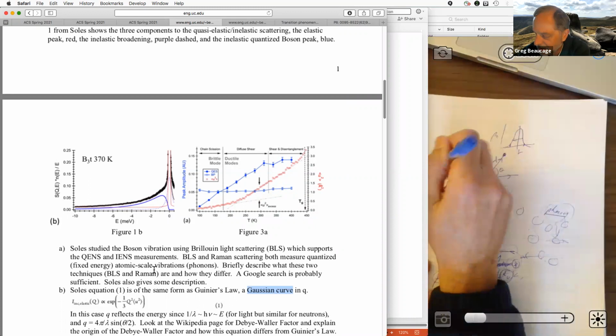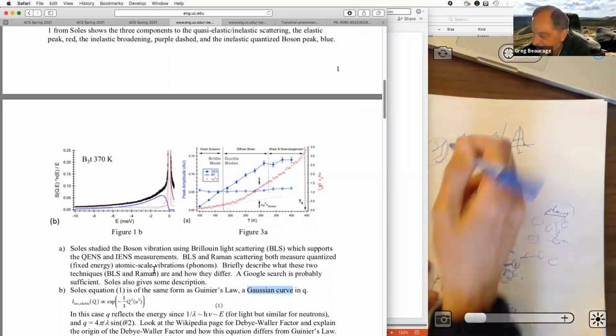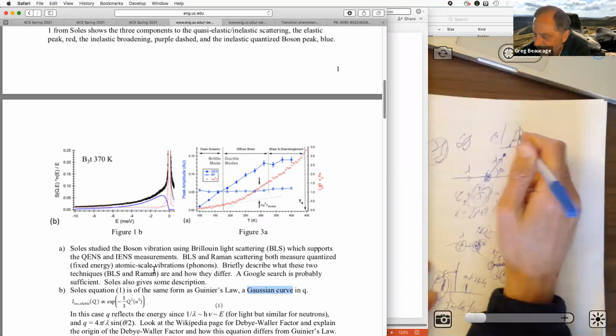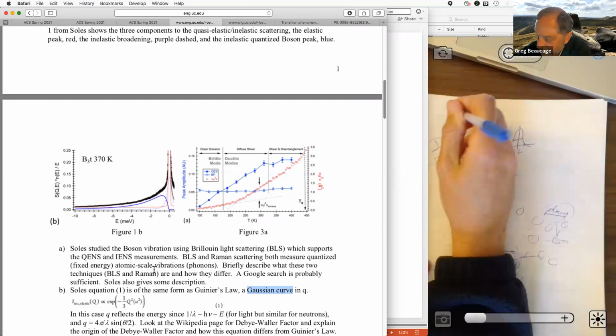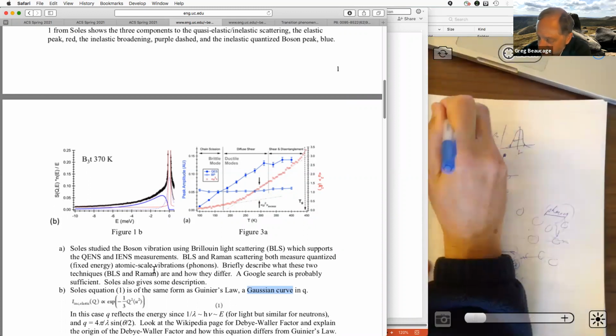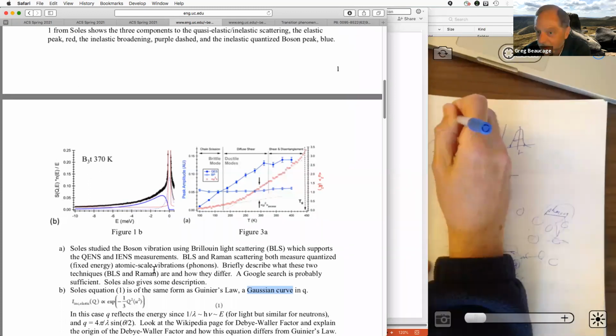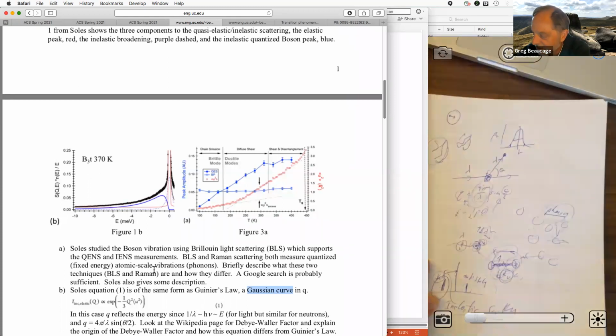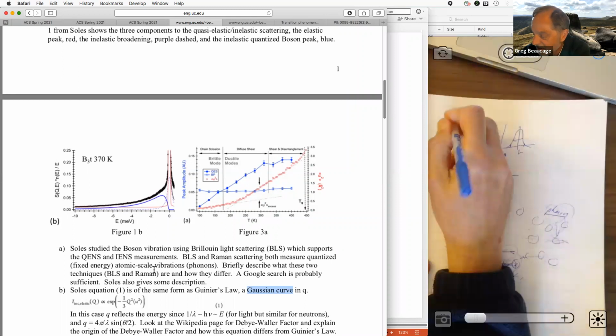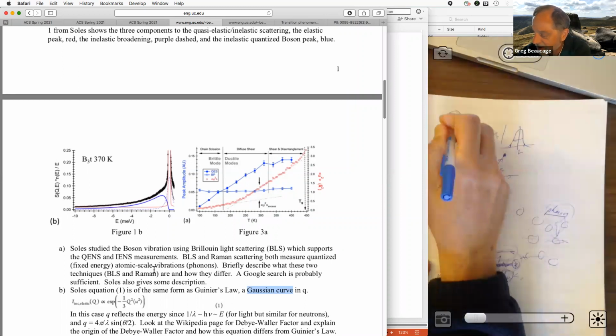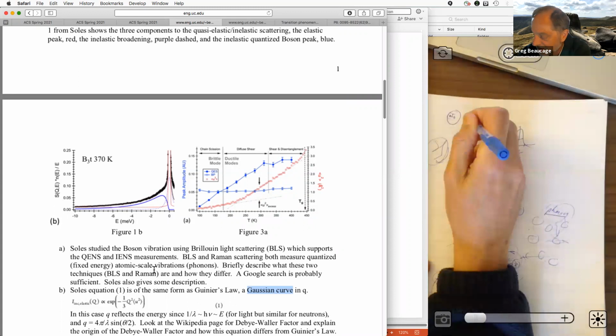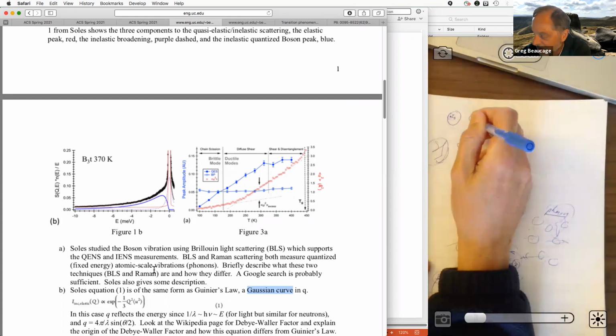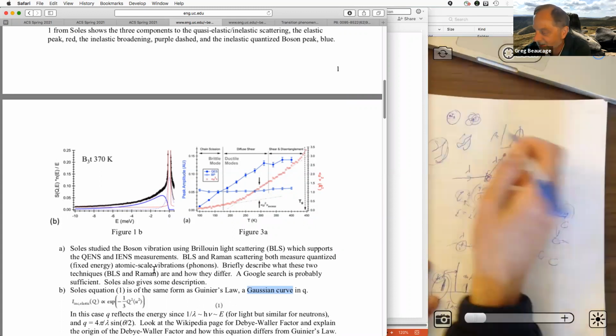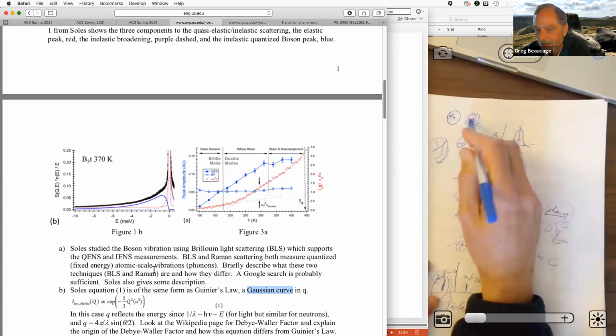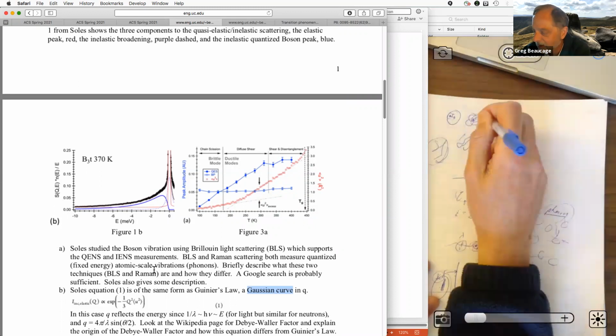It can be anything that's rotating ends up being a Gaussian. Even if it's a perfect sphere, because you're coming in with a beam and then you're looking at what's the density away from a point that was already in the sample, so this distance r. So your starting point would be at different points in the material. So even if it's a perfect sphere, it can have starting points that range. So you'll end up with basically a Gaussian cloud if it's moving around, it's thermally moving around, right?